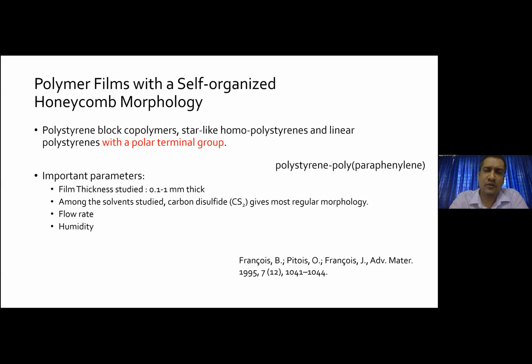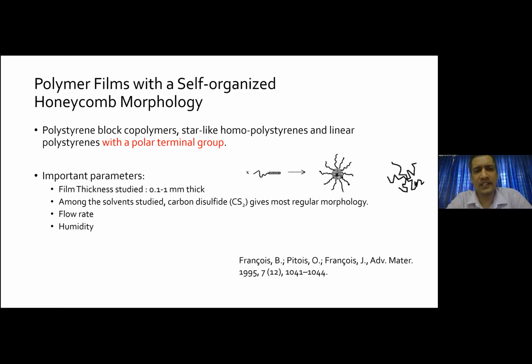So first they thought that, okay, anyhow, we need to have some kind of self-assembly once the water droplets are condensing onto the surface. So they thought of choosing block copolymers, polystyrene block polyparaphenylene, while the polystyrene is comparatively flexible. This polyparaphenylene is more of a rigid kind of polymer. So they thought that this polystyrene, polyparaphenylene tend to form some kind of aggregation into these kinds of structures when they are exposed to the condensing water droplets. The one which has free mobility can move, resulting in very robust formation of what is called breath figures.